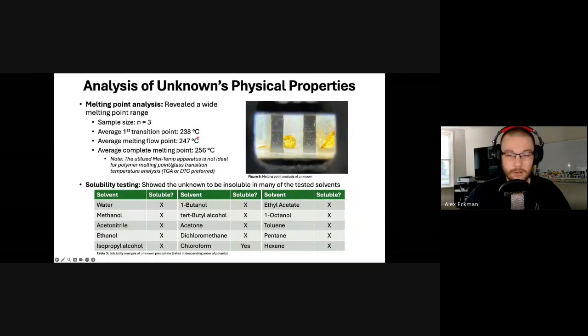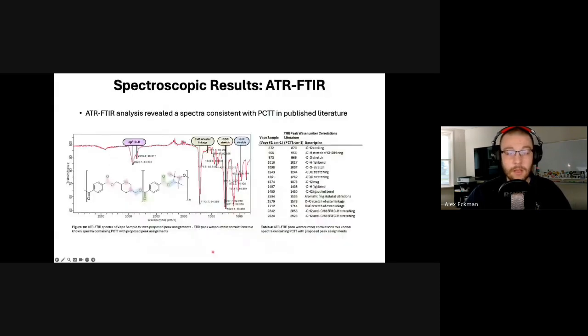We moved on to taking a look at the physical properties. Started off by doing a melting point analysis, realizing that this is not the ideal way to do a melting point on polymers. Ideally, we would have thermogravimetric analysis or DTC, but we were just utilizing what the university had. So we went ahead and got a rough range for the melting point and flow point. Looking into next, we wanted to see what this would dissolve into. We knew it didn't dissolve in hexane because that was the original solvent we were using. And after testing a wide range of solvents, we found that the only thing that it would dissolve in was chloroform, which was actually handy because we needed that for NMR. But we'll save that for a second.